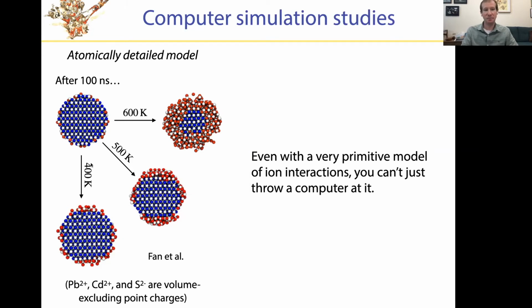They can make something happen by artificially heating the system up. And by the time you get to 600 Kelvin, you see quite a bit of exchange, but you also see that this crystal is becoming significantly more disordered. In some sense, it's beginning to melt. That makes this crystalline environment much more pliable, much more conducive to motion of ions and diffusion, et cetera. But in doing that, I've likely changed the underlying mechanism of this exchange process. And so those trajectories aren't really going to tell me what I want to know. What I want to know is, if I waited for a second, not 100 nanoseconds, but a second, what would be the natural dynamics of this transition?